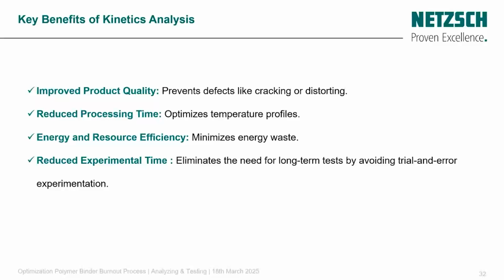So basically, as a key benefit, we can improve the quality of the product by avoiding defects like cracking, and also, as you know, any internal defect during the debinding stage will get amplified during the sintering. So that's why we are trying to control the conversion rate in this case, and also we reduce the time by optimizing the temperature profile while accelerating the production without losing product quality. For the energy, we minimize the energy waste by maintaining a constant mass loss, which enhances sustainability and aligns with the European regulation. And also, we are trying to avoid the trial and error approach, which speeds up the whole process.